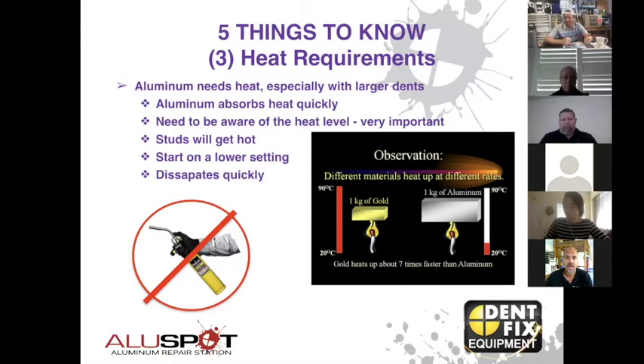Using the heat gun that comes with our DX and DXE units is recommended, but it's also important to know where you're at with your temperature. So we also provide a digital thermometer that allows you to shoot the laser onto your area and get a very accurate reading. The studs will get hot when you heat up the panel. Let's say you're at 275 or 300 in that range, that's a hot stud. So just keep that in mind when you're playing around with it with your fingers. But that heat should dissipate fairly quickly out of aluminum. It'll heat up quickly as well. So just be careful, because you can go from 400 to 600 really easily.